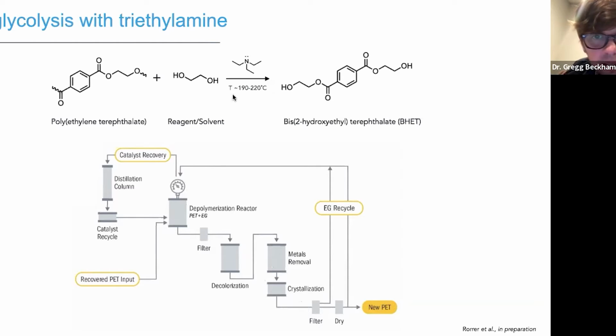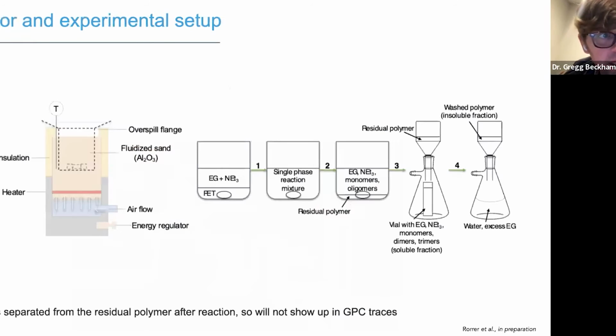Fortunately, this is a volatile catalyst, and so catalyst recovery is quite straightforward. If you release the pressure of the reactor at reaction temperature, the catalyst is volatile and can then be distilled and recycled very easily. This is work that's led by Bob Allen at NREL, I should mention, as well as Nicholas Rorrer. We're working on writing a paper on this now.